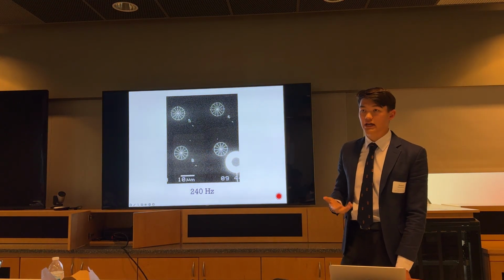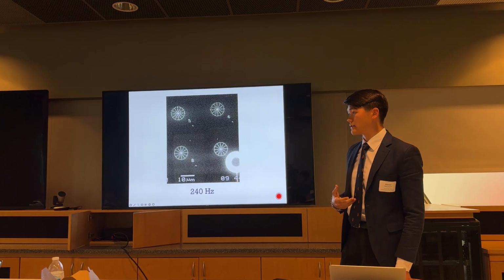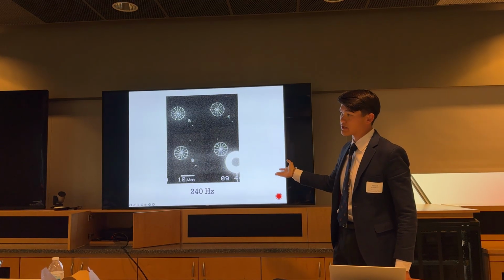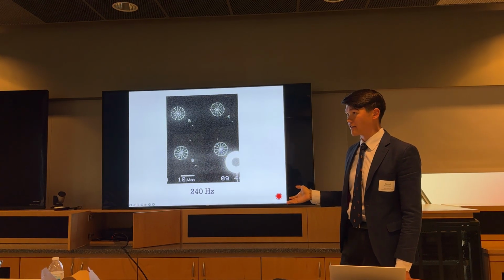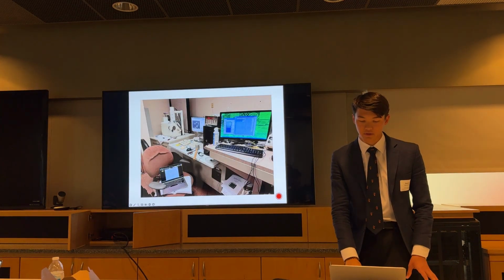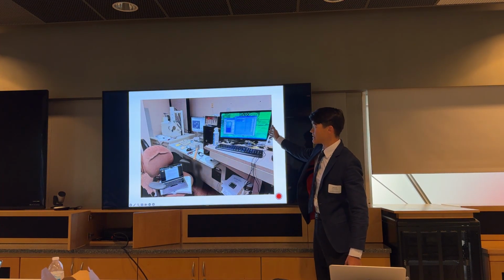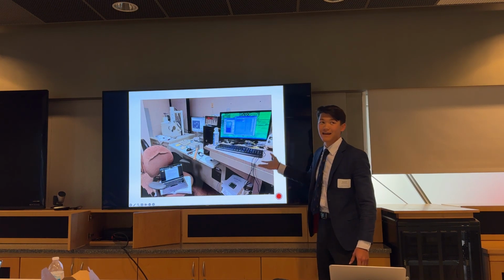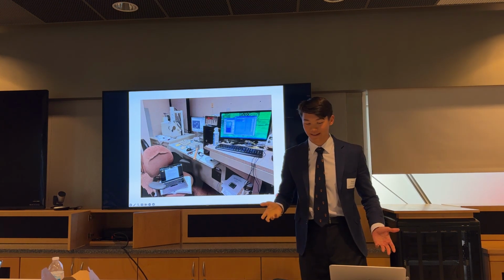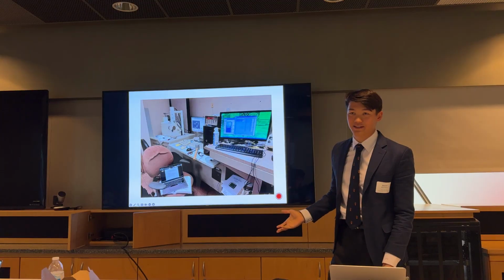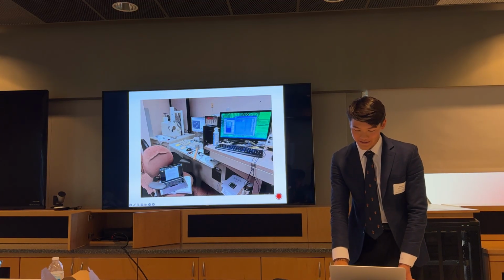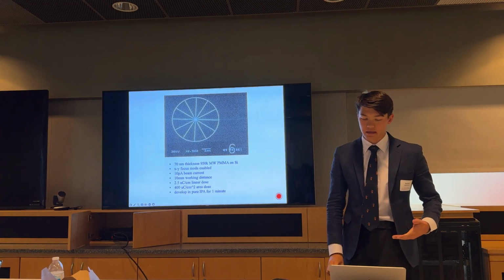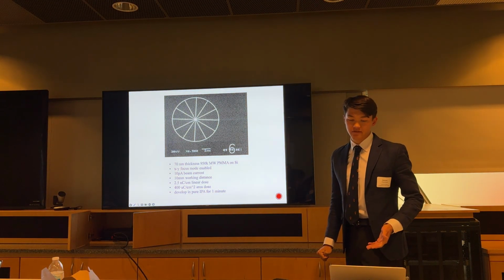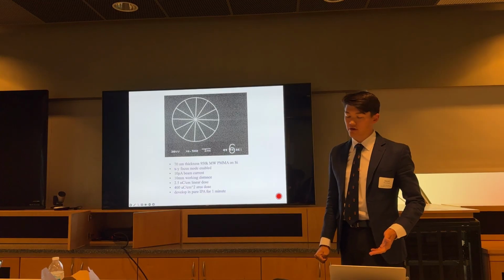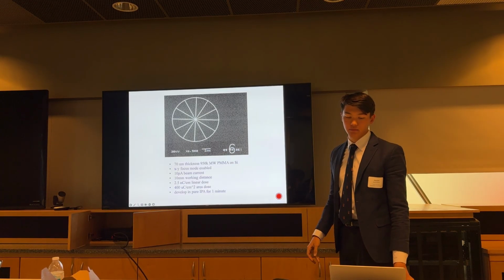And by realizing that that was the cause, we could calculate that the noise was roughly 240 hertz. And that was very useful in tracking down the final issue, which was indeed an equipment issue. It turned out that this specific monitor connected to the setup was causing interference, and simply unplugging the monitor fixed everything. Issues like this, you never know what causes them. So with the working setup, I then proceeded to optimizing parameters for PMMA electron beam lithography, and these were the parameters I ended up with.